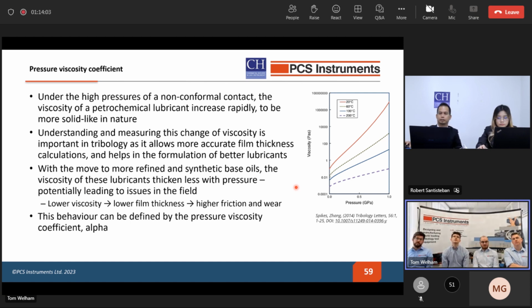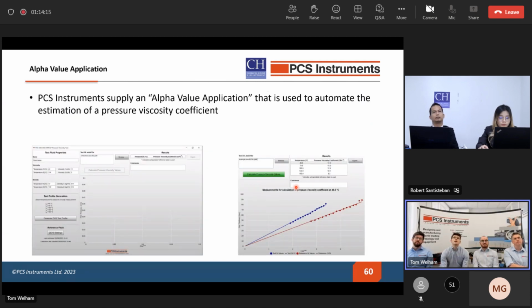And if this isn't well understood, that could lead to high friction and wear. This effect can be described with a single parameter called the pressure viscosity coefficient, or alpha value. And using PCS's alpha value application, the film thickness results from a test can be fitted to a model for film thickness, providing a simple method to obtain a lubricant's pressure viscosity coefficient.